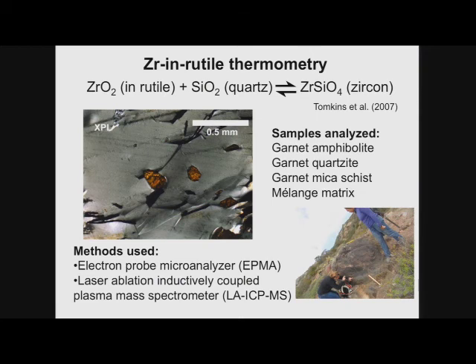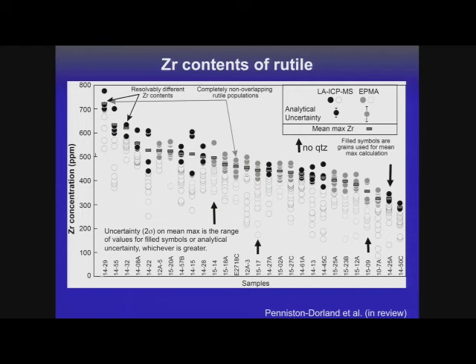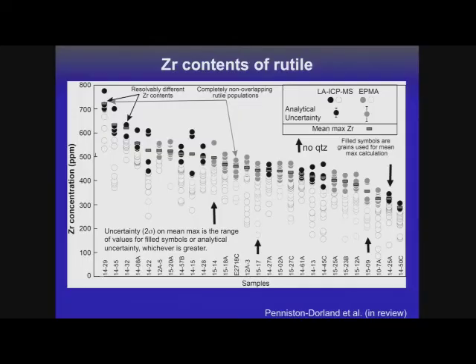So we've got a couple of different methods. A lot of different rocks that are found in this melange zone. And it's a lot of data, and I apologize, but essentially each of these vertical columns represents a different sample. First of all, you can see that not every rutile in a rock records the same temperature, all right? There are a lot of processes like diffusion and growth zoning that can act to decrease the amount of zirconium, or to have a lower zirconium content in a rutile. So our goal is to look for the peak or maximum zirconium content, but we don't want to take just one analysis because we can also have analytical artifacts, or we could have rutiles that are actually isolated from the reactants involved in the reaction. So we've developed this method whereby we average these top four measurements, and that's what's shown by each of these gray bars for each sample. We call it a mean maximum zirconium method.